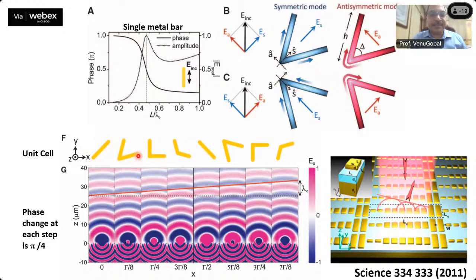Now, each one of these antennas is so designed such that the phase change from one to the other is about pi by 4. So from one end to the other end, we are changing the phase of the incident field, or the scattered field, by 2 pi. Right. So you can get a phase front which is aligned at a designed orientation, right? So that's what is shown by this red line here. So now what we're doing is we're actually manipulating the phase of the scattered light by patterning the surface of our substrate. These patterned surfaces, which can be used to control the wavefronts or the phase of these incident beams, electromagnetic radiation, are known as metasurfaces.